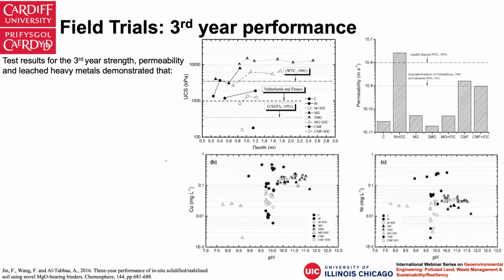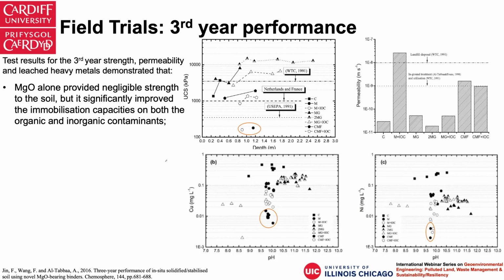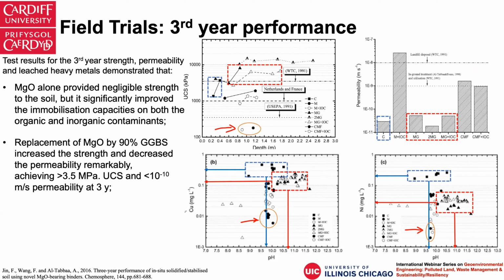A few important findings were reviewed from the lab analysis. First of all, magnesia alone can provide negligible strength. As we just mentioned, there's almost no solidification, but it significantly improved the immobilization capacities of both organic and inorganic contaminants, as we can see from these circles. The metal leachability is the lowest among all of these binders. But if you do need solidification, you need strength in your treated soil, then you simply replace magnesia with this industrial byproduct, GGBS.